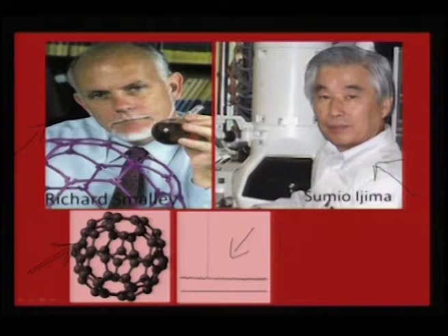In this case what you see here is the mass spectrum, which gives just one single M/E peak for this fullerene, which does not come in the 0 to 100 range, it is beyond 500, which usually we might be tempted to ignore, especially when you talk about carbon clusters. You would not like to look at a higher M/E ratio, and this M/E ratio comes beyond 500 mass, and this single peak actually brought the discovery of fullerene into focus. Otherwise there was no way they could map it.